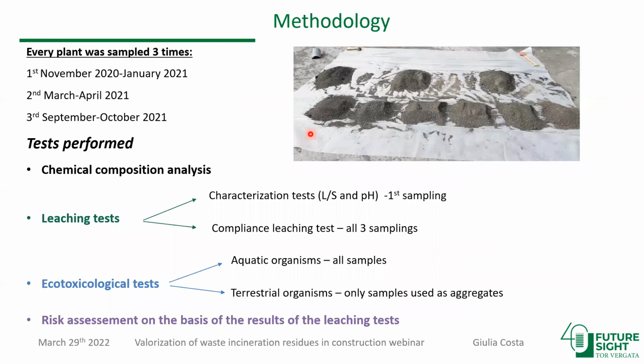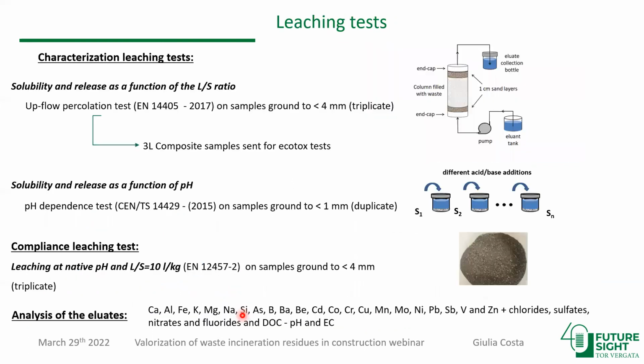Now, these samples were taken from these plants in 3 different times of the year. And on each sample, chemical analysis was performed. Then leaching tests were carried out. Full characterization ones only on the first sampling, compliance leaching ones to all 3 samplings. Ecotoxicological tests are being applied to all 3 samplings, looking at aquatic organisms and terrestrial organisms. And risk assessment is being applied on the results of leaching tests.